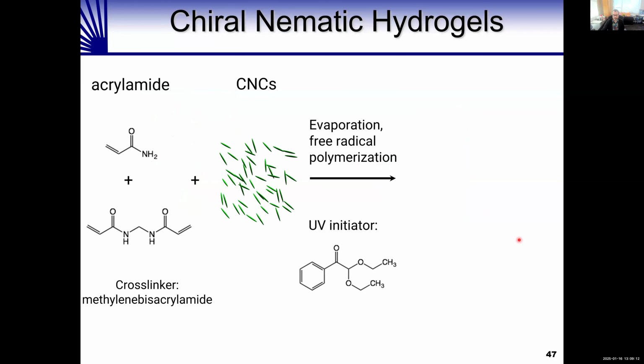So this is what we did. You don't have to worry too much about these molecules, but we took a common precursor to polyacrylamide, which is a well-known hydrogel. We took acrylamide and this molecule on the bottom, which is a cross-linking agent, and combined them in water with cellulose nanocrystals and a free radical initiator for polymerization.